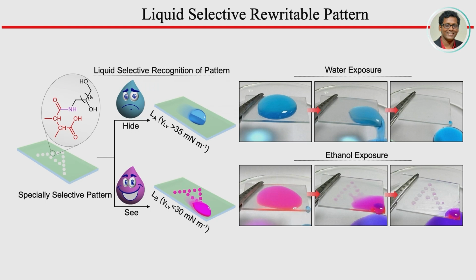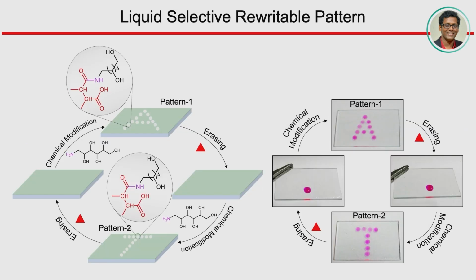So taking advantage of that, what we did, we made a spatially selective pattern. Now this pattern is only visible to ethanol, but not to water. So it's the same pattern, same interface, one liquid can see the pattern, the other liquid cannot really see it. That is very difficult to achieve, but you can see, we are putting the water droplet and you don't see any trace of the water droplet here. But when you put the ethanol, then it can find those spots and it can take the shape of that arrangement, right? And taking advantage of that, you can recreate or rearrange this functional group on the top surface repeatedly, right?